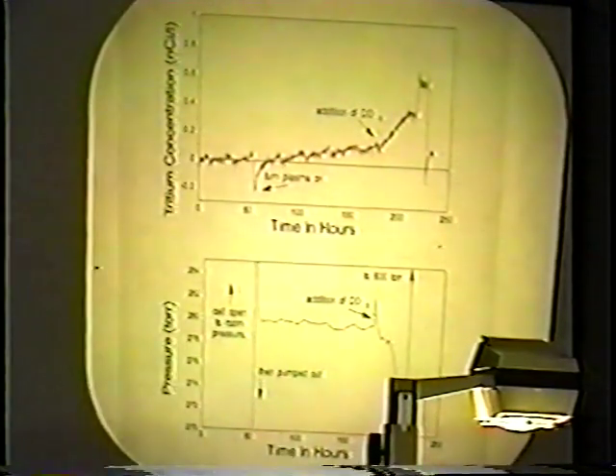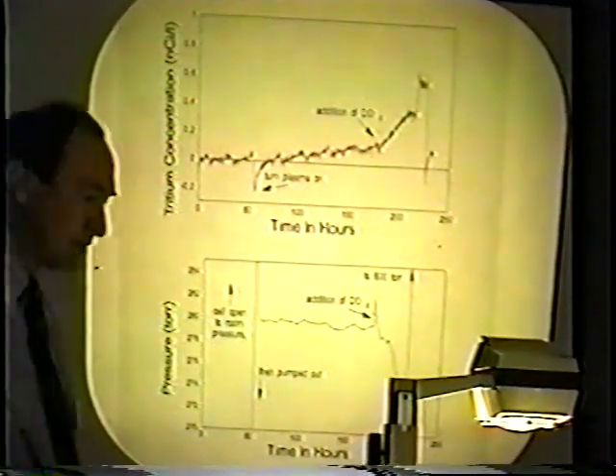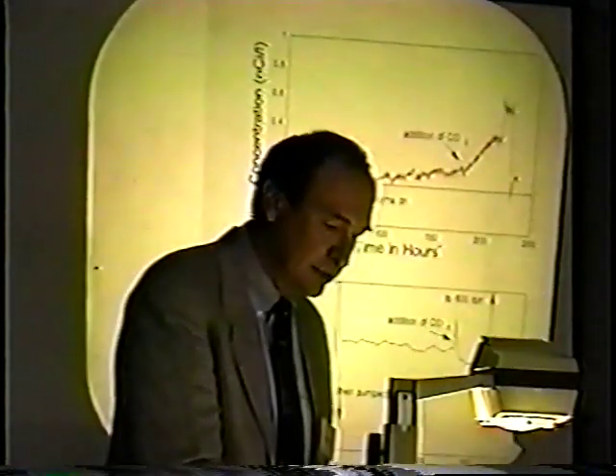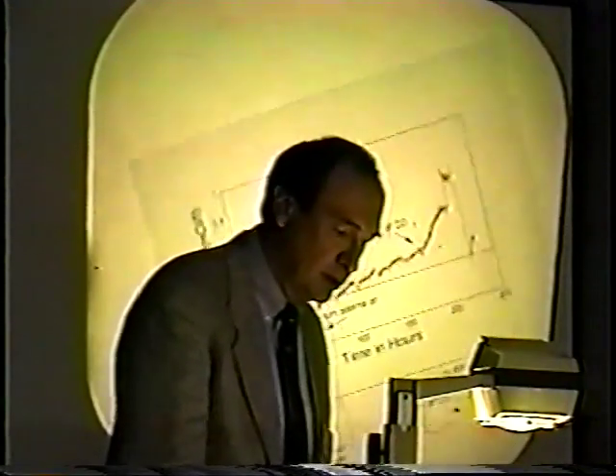Now, there's another feature to this. If you have a system where the wire is fully hydrided and the rate is going off like this, which was another one we did right after this, and you add the CO2, there's no change. So really, the CO2 isn't a panacea. It's just a hydride aider, but doesn't seem to help the rate, because whatever the rate is in that material, that's what you'll get.